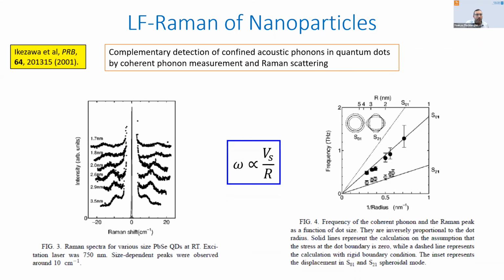And intuitively, this was explained to me by Professor Igor Lubomirsky from the Weizmann Institute, where he said, think of it like this. If you have a certain speed of sound for this material, and then you have a certain radius for your nanoparticle, the frequency is basically going to be set by the speed of sound divided by the radius. So you have this linear relationship between the low frequency Raman scattered frequency and 1 over the radius, as this group showed.